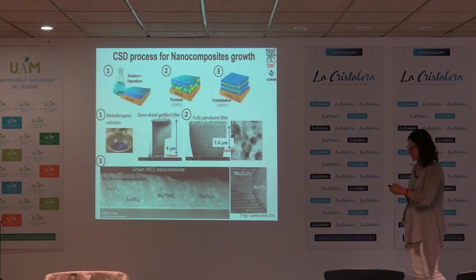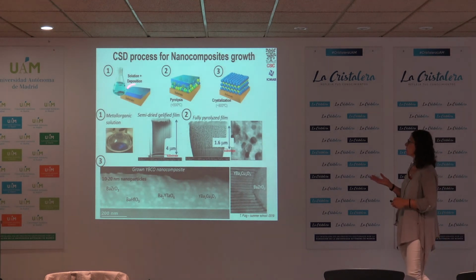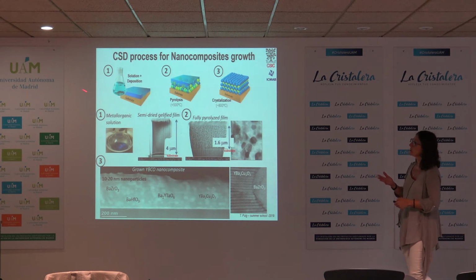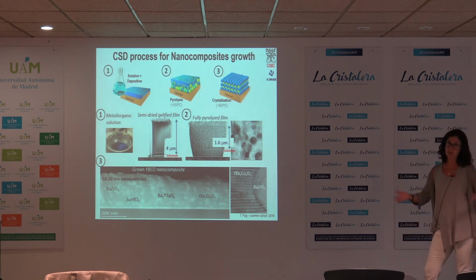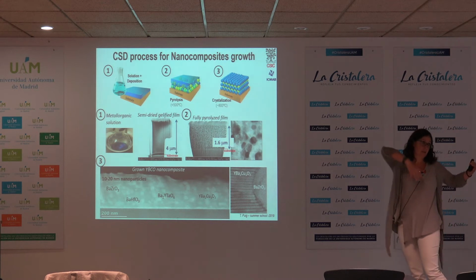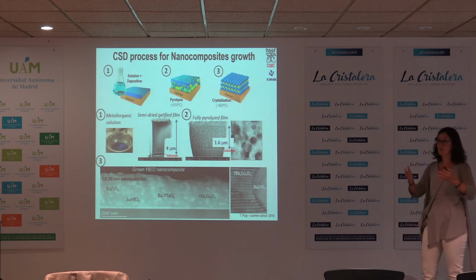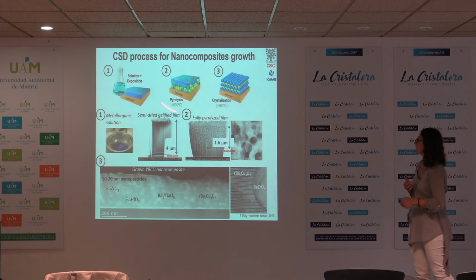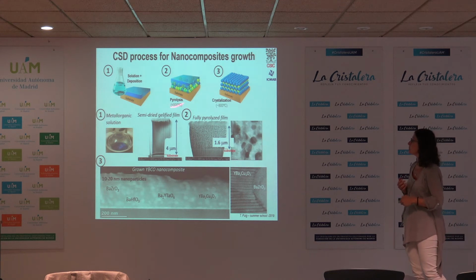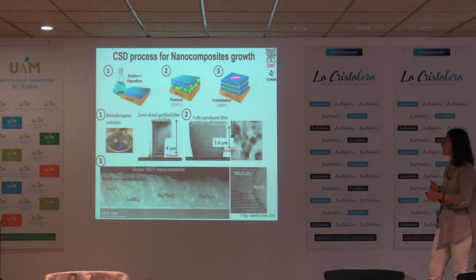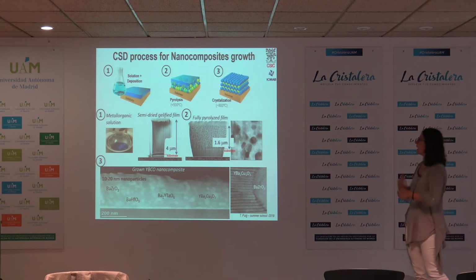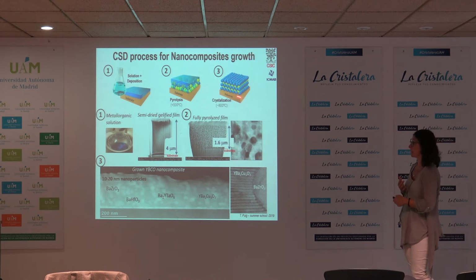In the chemical solution deposition, we have a solution we have to deposit. This solution is a metal organic solution. We want to get rid of all the organics because at the end we have to end up only with the yttrium, barium and copper. This is done at 500 degrees or so, which is called the pyrolysis, and then we go to the crystalline YBCO as a second process at higher temperatures.